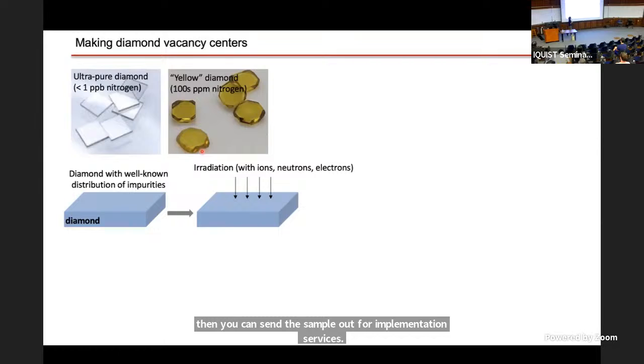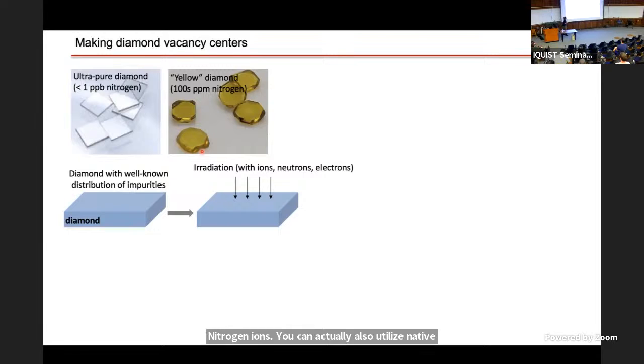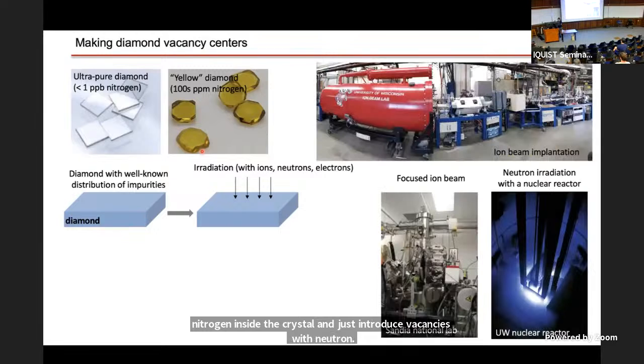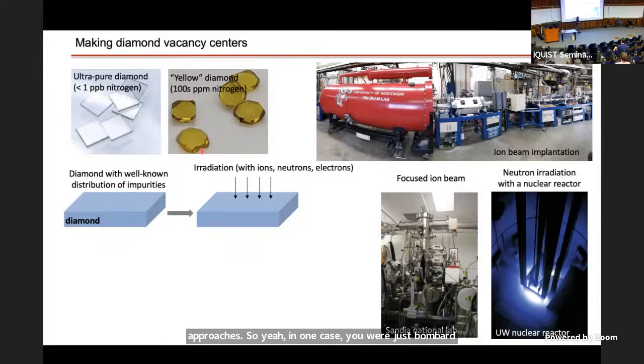You can do this with nitrogen ions. You can also utilize native nitrogen inside the crystal and just introduce vacancies with neutron and electron irradiation. I have examples of all of these approaches. In one case, you would just bombard the crystal with nitrogen ions. There's a picture of our ion beam lab at UW-Madison. We collaborate with Sandia National Lab to utilize focused ion beam, which is a variation of this technique. The idea is that you have beam focusing optics for your ion beam, so you can place your ions where you want, up to a point, within the diamond crystal. And then there's a picture of our nuclear reactor.